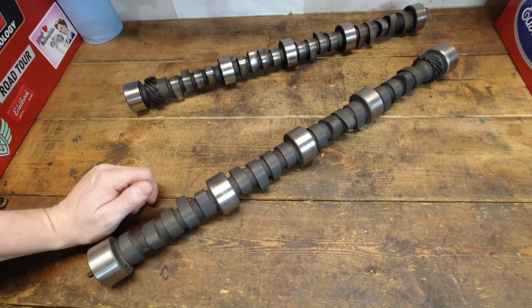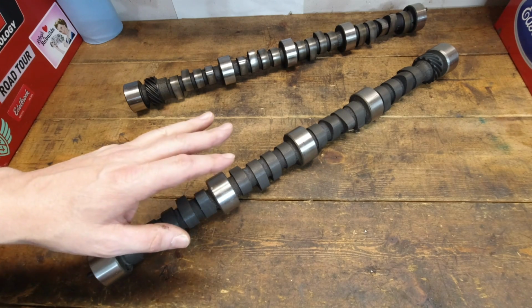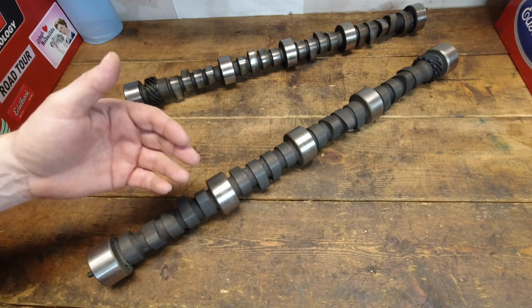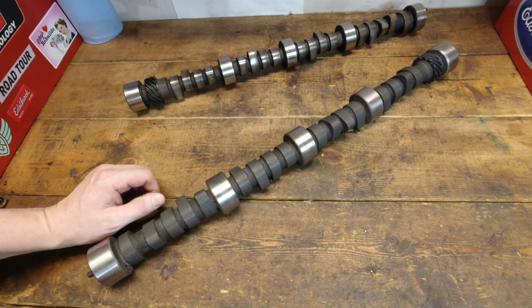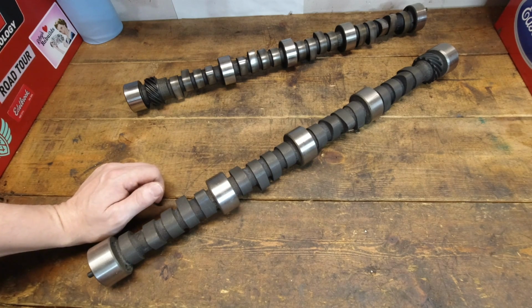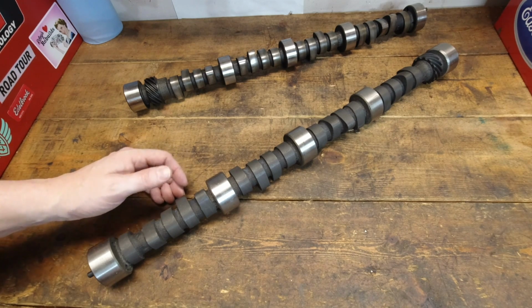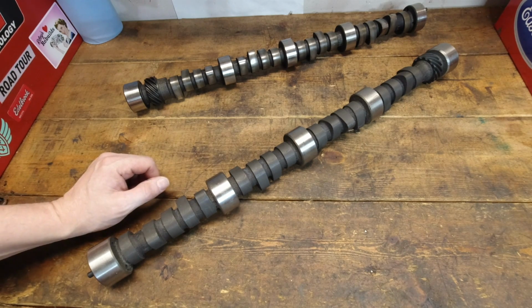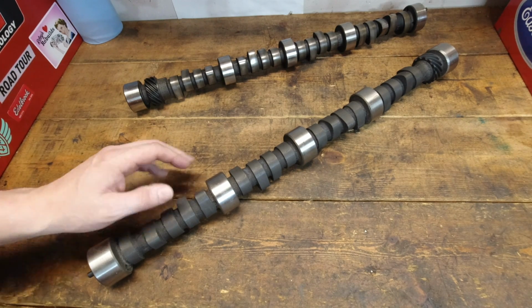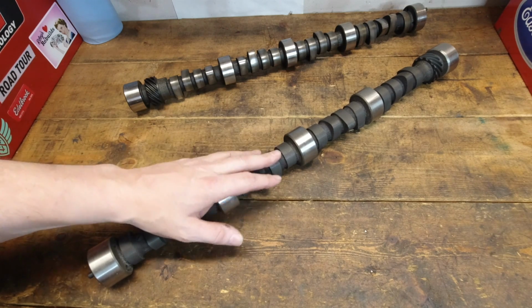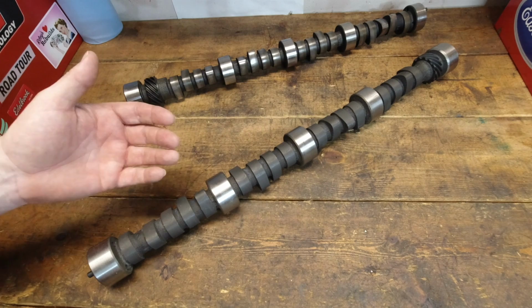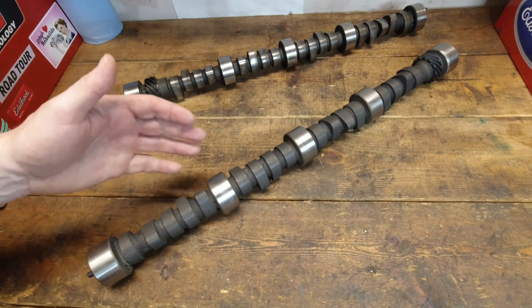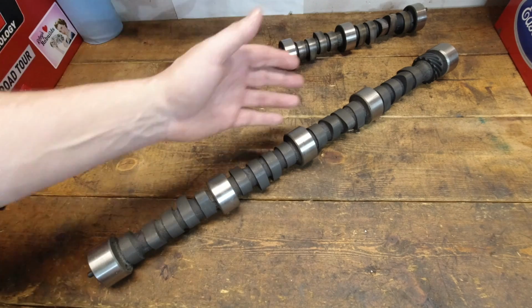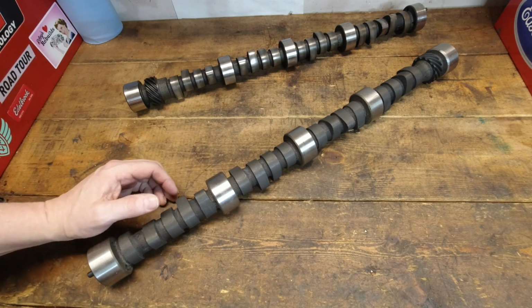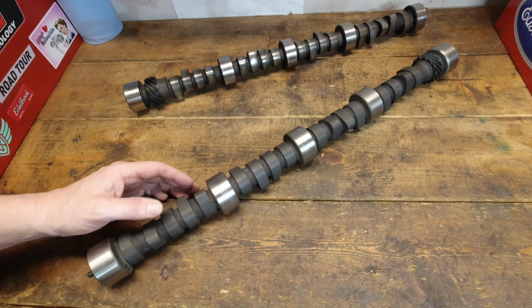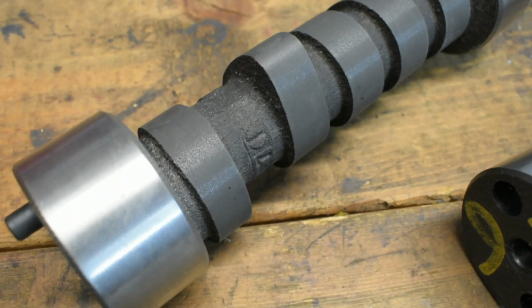Again, it's a question that we'll confirm with Billy, but before that cam core is ready to be hardened, typically they have an HRC on the hardware, the Rockwell scale, of about 34 to 36, I believe, is the general range that those cams are. Once they are done and heat treated, and in this condition here, this one's a ground camshaft, but once it's done and ready to go to that supplier to be ground, typically they have the HRC level around 48 to 55. That's generally the range.